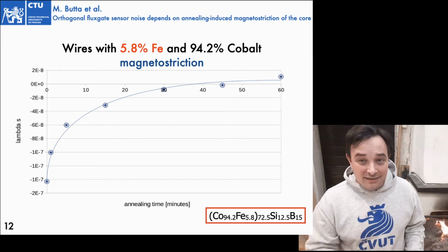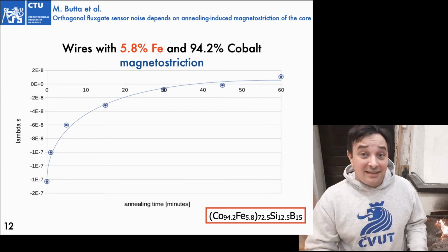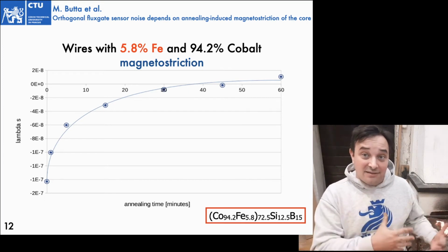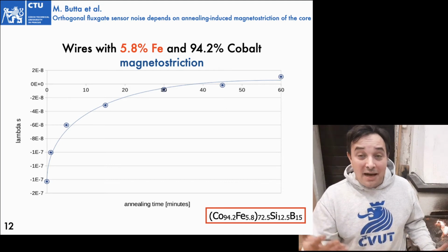But what happens when I anneal the wire? When I anneal the wire for a longer time, even 1 hour, 50 minutes, since I start from a larger negative magnetostriction, after 1 hour I'm almost at zero magnetostriction. So, what to expect from the noise when I use these wires for my sensors? Well, if my theory is correct, I should expect a larger noise when I use the as-cast wire, because the magnetostriction for these wires with 5.8% iron instead of 6 is larger. But then, after 1 hour annealing, the magnetostriction is almost zero, so the noise should be lower. It should not rise back as it did with the other wires.